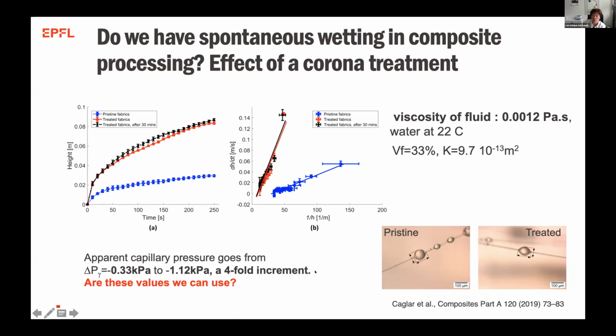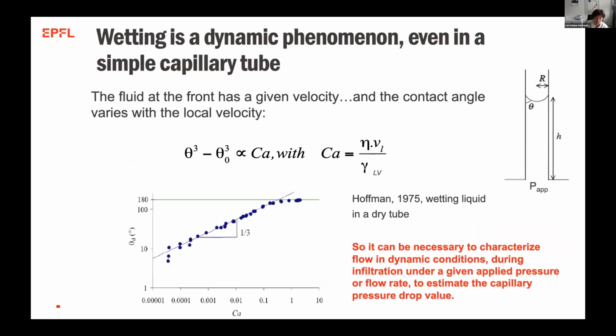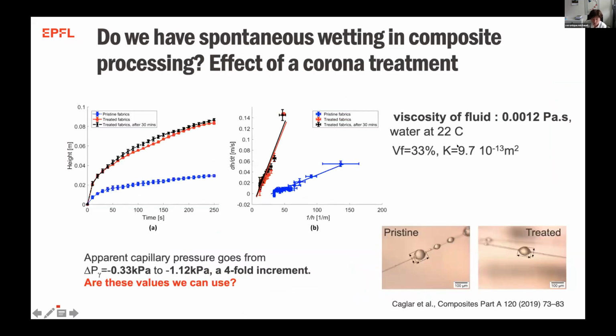So are these values we can use? So we have measured this capillary pressure drop. Can we use this value? Of course, the answer is no, otherwise I would not be here. And in fact, the problem is this value that you measure is with a given velocity, and the velocity was reasonably low. You can calculate it, since you have the height versus time.